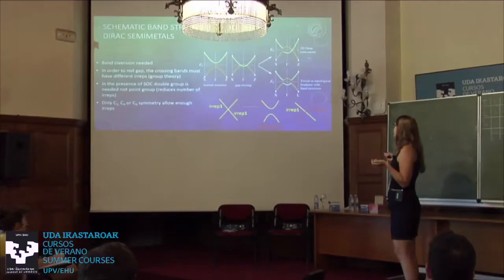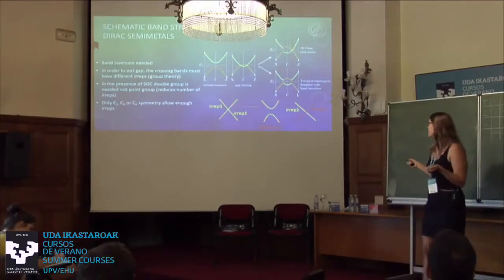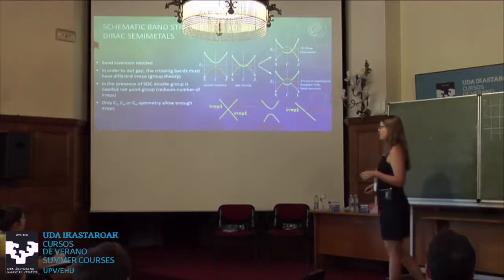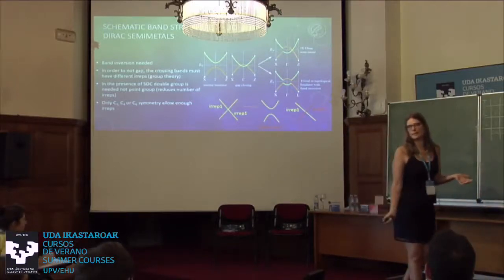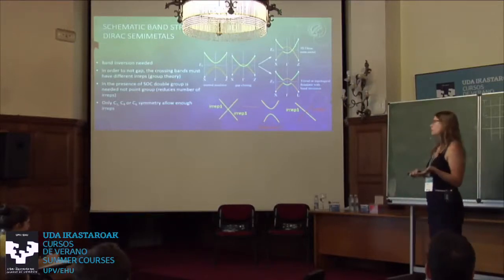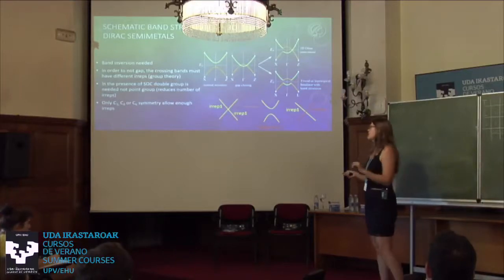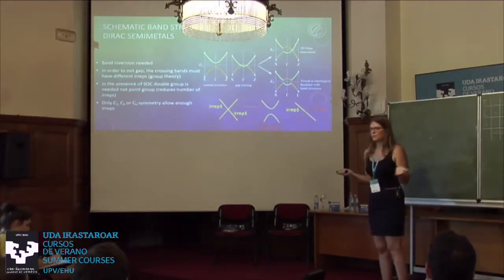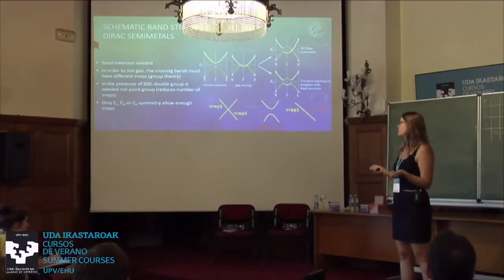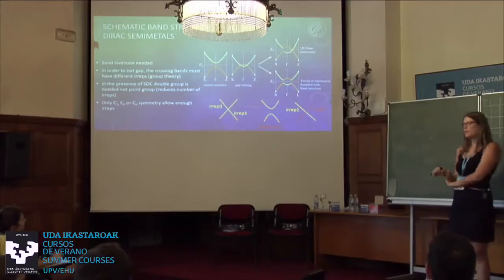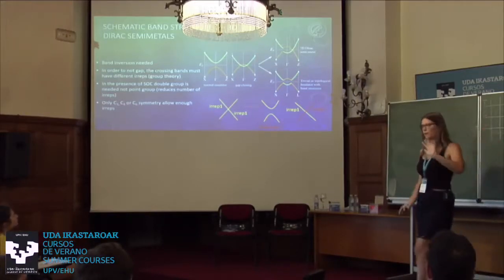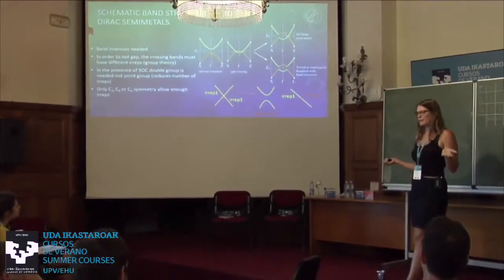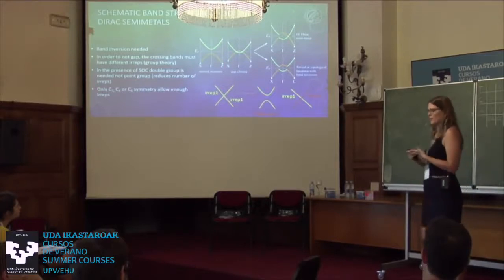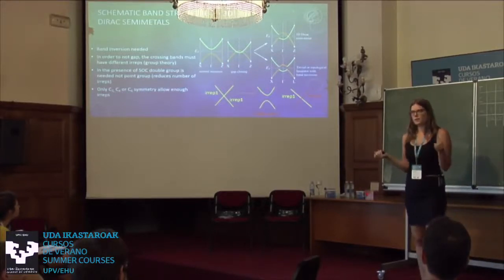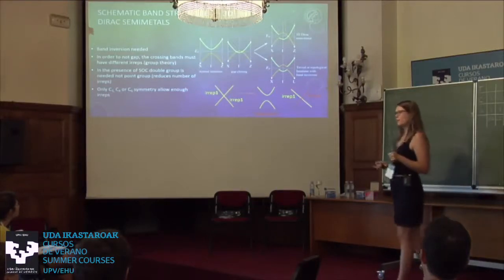And so if you want to have a crossing left in your band structure and have a 3D Dirac semimetal and don't want to have it completely gapped, you need to have two different IRREPs crossing. And for this, it needs to be possible by symmetry reasons that two bands have two different IRREPs. If you even include spin-orbit coupling, so if you look at double groups, then this reduces the number of symmetry groups where this is allowed to only the ones which have C3, C4, C6 symmetry. Okay, so for me as a chemist, this means I can skip everything monoclinic, everything orthorhombic, everything triclinic, because this doesn't have the symmetry element. And I can focus my search on cubic, tetragonal, or hexagonal materials. Okay, so the first guideline rule is, we need high symmetry.